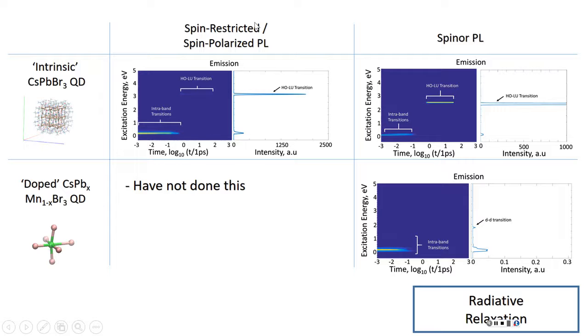So if we look just at our pristine or intrinsic dot, spin restricted calculation, we excite right away, and then as it relaxes to the band edges, that's what happens during this time. Down here, you can get possible intraband transitions or luminescence from like LUMO plus 10 to LUMO plus 8 or something. So that's what these describe. And then at about 1 picosecond, electron and hole relax to the band edges, and that's when you get your HOMO-LUMO transitions. This figure basically says that the interband transitions have higher oscillator strengths, are brighter than the HOMO-LUMO transition for the quantum dot, which is interesting.